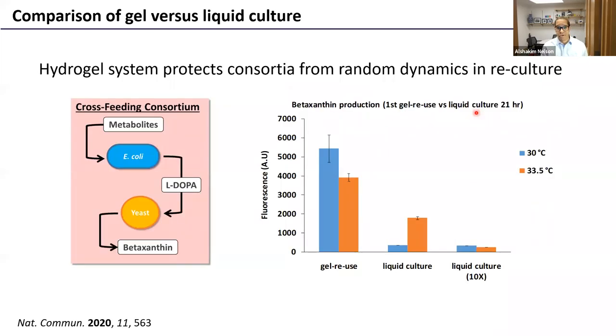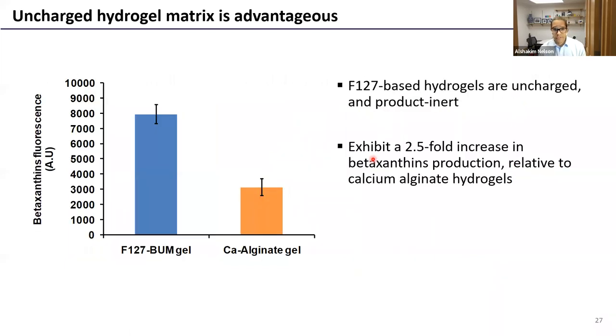This is just comparing betaxanthin production in the gels versus liquid cultures. We do see that the production of betaxanthin is higher in the case of reuse when we use the gels versus liquid culture. And then finally, just to compare betaxanthin production from our F127BUM gel versus calcium alginate gels, there is an advantage to using our hydrogels. And we believe that the real advantage, there are two advantages here.